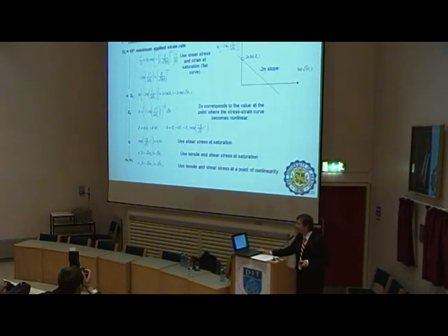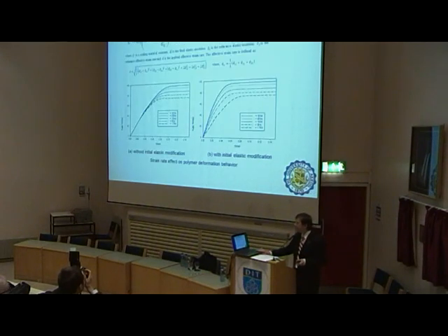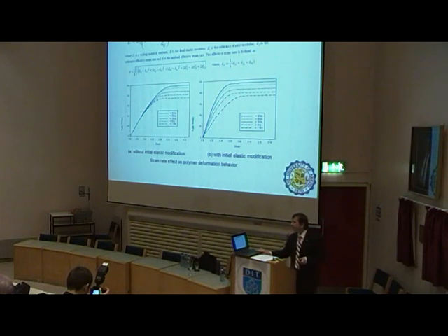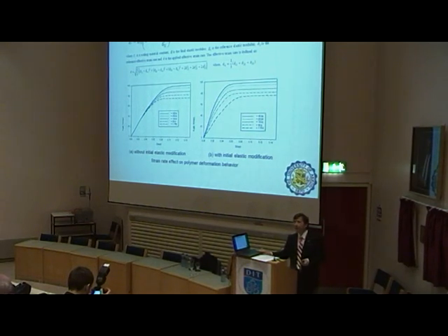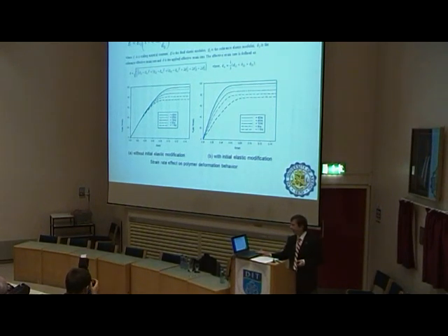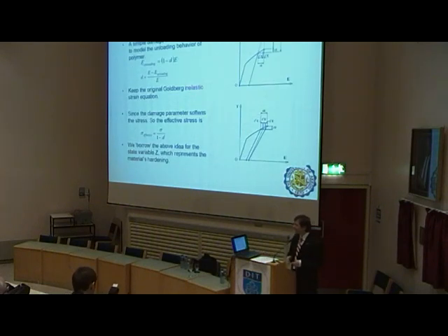And of course, this is not finished. We also have to add some damage that is involved in the material itself as a matrix. So the damage is reducing the Young's modulus. You can see that the more the damage, the different slope, even at the beginning of the stress-strain curve, is obtained, and that needs to be related mathematically. And it was captured using the damage parameter, which is basically defined using the Kachanov type of definition.